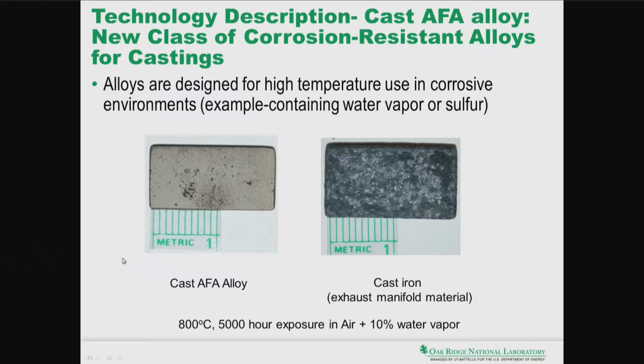So let me just start with a brief description of the technology. What we're talking about is a new class of corrosion-resistant alloys, and these alloys are designed for high temperature use in corrosive environments. On the left, I show here a piece of material, cast alumina-forming alloy, that has been exposed to a temperature of 800 C for 5,000 hours in an air plus 10% water vapor environment. On the right-hand side is a cast iron subject to the same conditions, and you can see the difference in the surface quality after the exposure. So clearly, these alloys are able to resist the environment containing water vapor and/or sulfur.